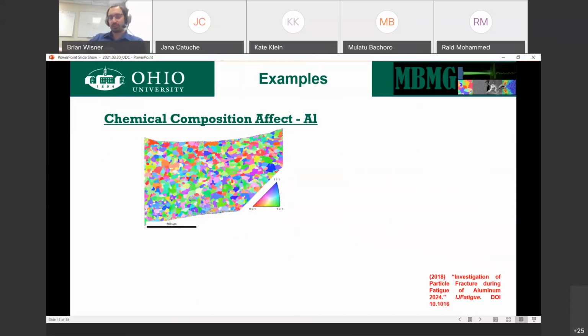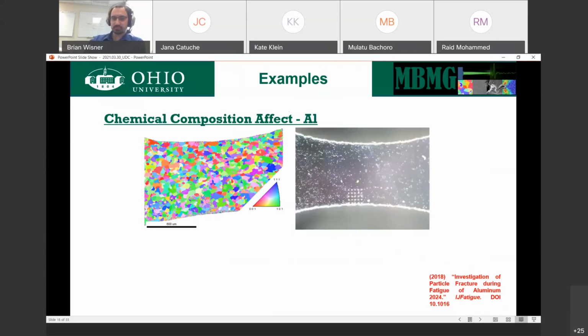In this case, I'm focusing on this one because I've done some exploration of additive manufacturing for an aluminum alloy as well. And this gives us a nice analogue to the kind of mechanisms that might happen that we can look for in the additive realm. We take this, just to give an idea, this is the microstructure of the whole sample. I'm actually only monitoring this small region in here. So the spacing between each of these dots is on the order of 50 microns. And I'm looking for what's going to happen to these particles that result from the process.